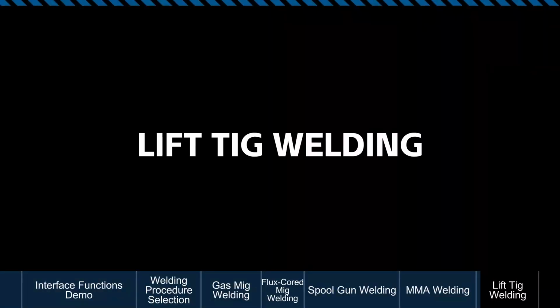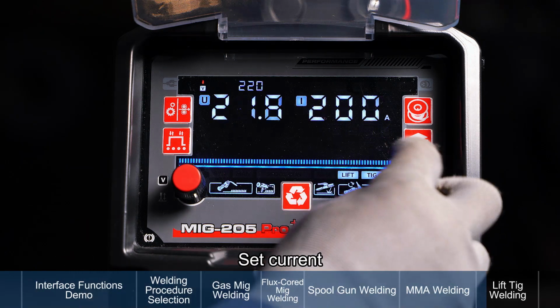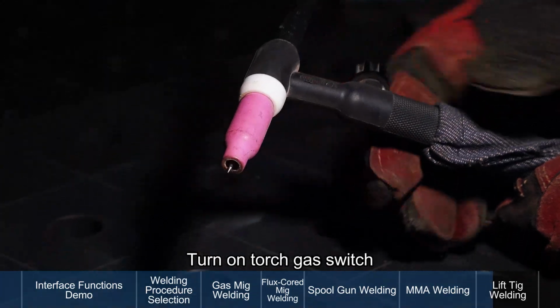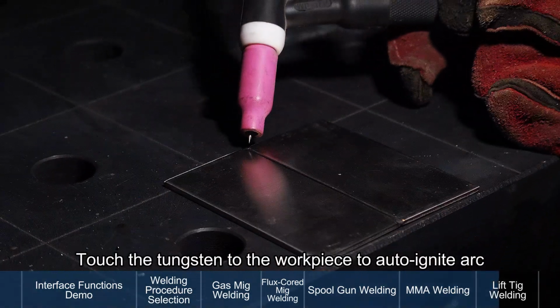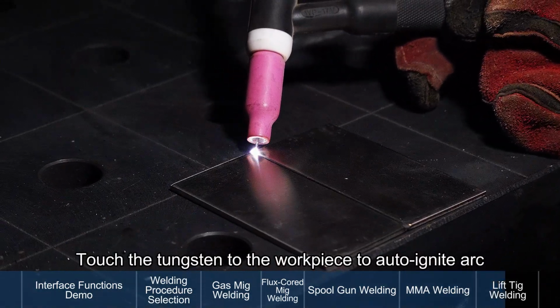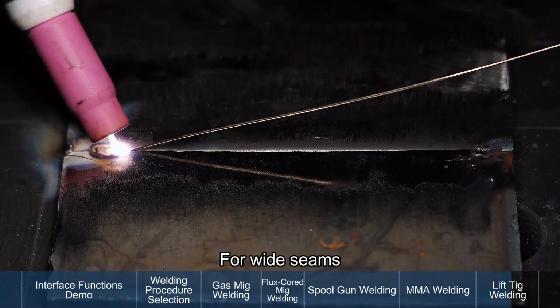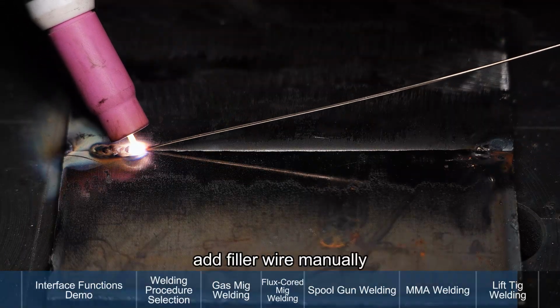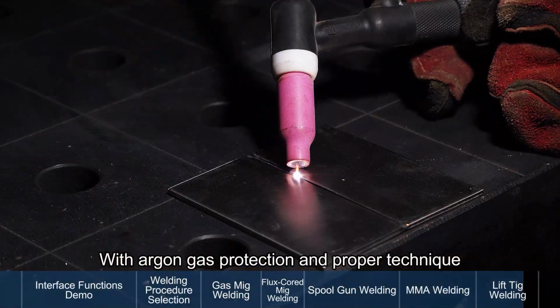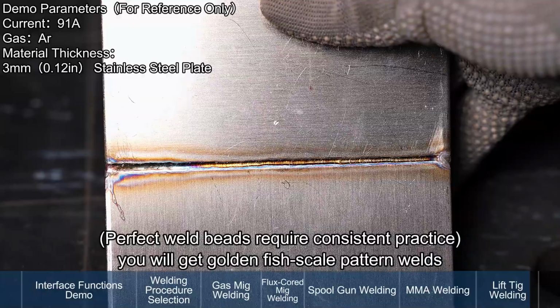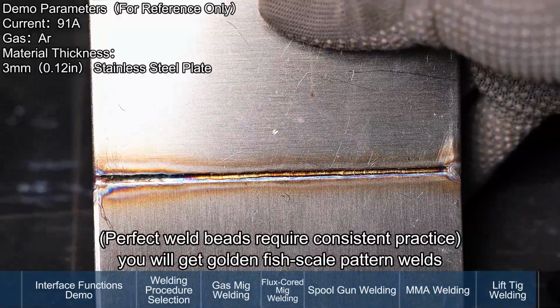Lift TIG welding. Switch to lift TIG. Set current. Turn on the torch gas switch. Touch the tungsten to the workpiece to auto-ignite the arc. For wide seams, add filler wire manually. With argon gas protection and proper technique, you will get golden fish scale pattern welds.